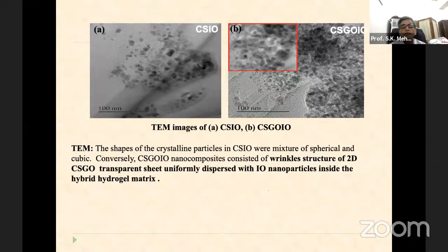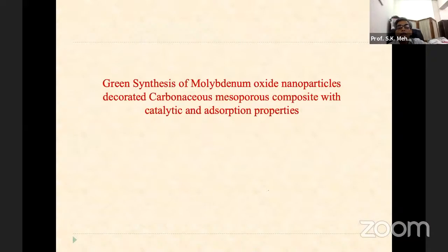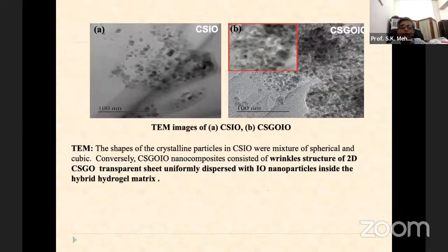So this is a comparison of the TEM, because we wanted to see the size also. So we have a 2D structure, and we have a transparent sheet with uniformly dispersed iron oxide nanoparticles inside the hybrid hydrogel matrix. So a very interesting study. It is already published also, so I am not showing that.